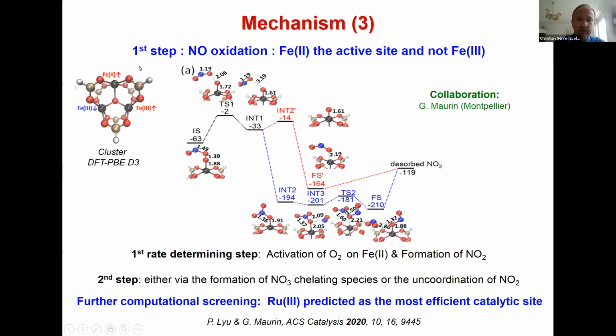But of course, this is very difficult to model, a configuration of the spin state of a trimer with a lot of d electrons. So there will probably be a strong challenge to have a full picture of the mechanism in the future. However, what they have also tried is just simply to replace one iron 3 by ruthenium 3 species, and they predicted that it could strongly enhance the efficiency of the catalytic reaction.